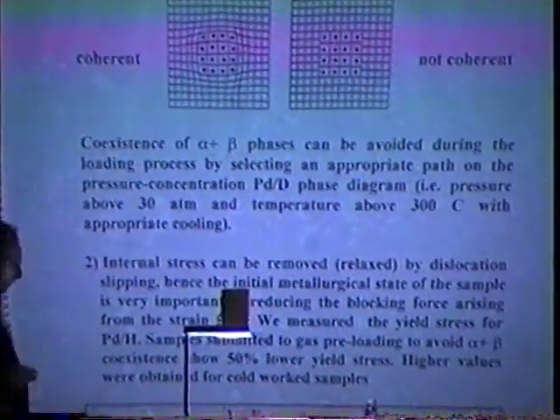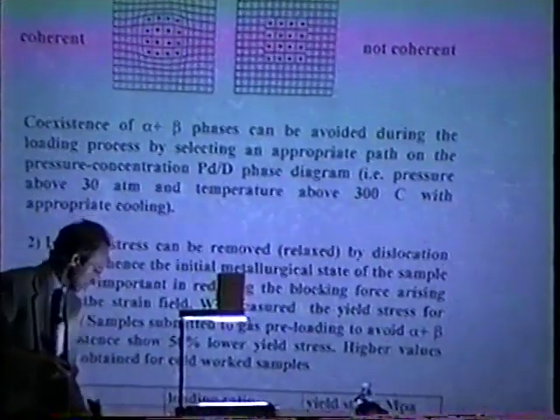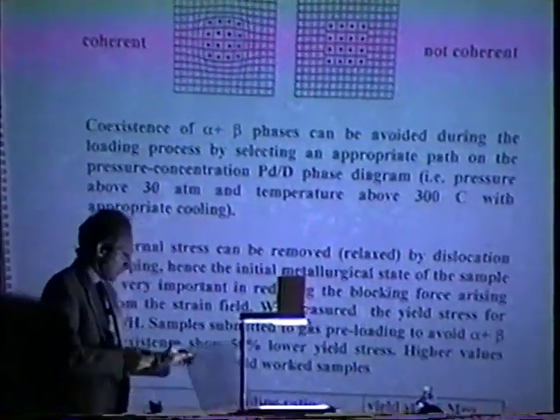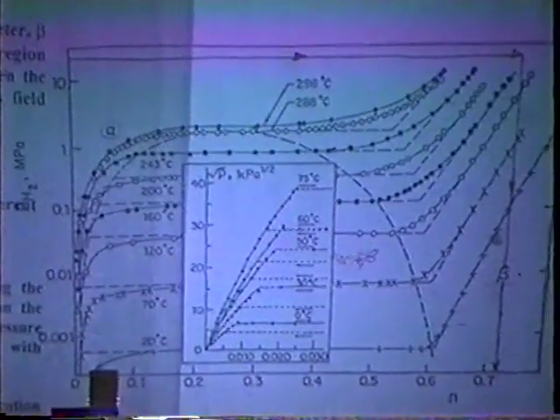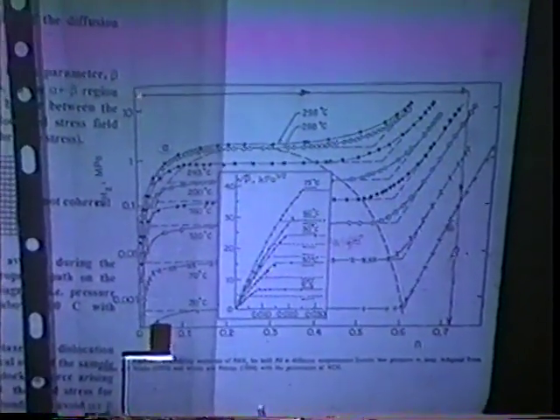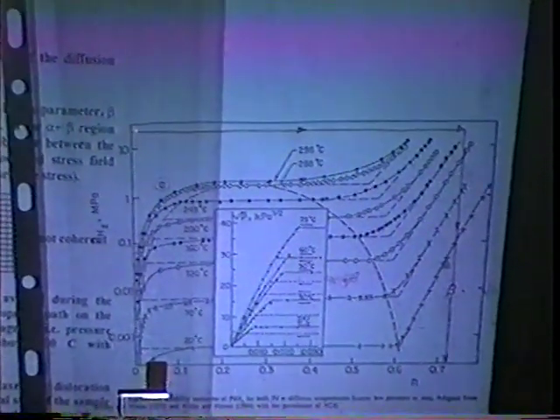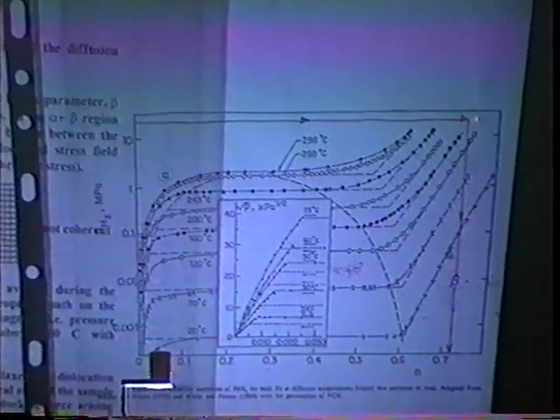Anyway, to avoid this coexistence of stress, we prefer to load following this pathway. So we heat the system up to 350 centigrade with a pressure of about 30 atmospheres, and then we wait for a time long enough to move the concentration inside the medium above the beta minimum value.